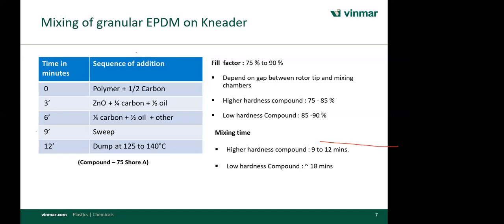So it depends. The fill factor in the mixing of any synthetic rubber is important in the case of a kneader. It depends on the gap between the rotor tip and the mixing chamber. So if your kneader rotor is old, please take care of the loading. Generally, the lower the hardness, the more you have to fill. And if the hardness is high, then the fill factor is less. Again, mixing time depends. There is no standard mixing time for kneader mixing. It depends on the hardness of the compound. For high hardness, usually 9 to 12 minutes. But for low hardness, we recommend to mix